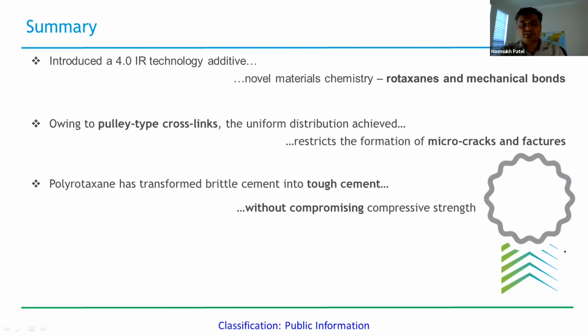I have also demonstrated the effect of polyrotaxane, just 1 weight%. It actually transforms brittle cement into tough cement without compromising the compressive strength. Compressive strength is also very important. We have to have some kind of compressive strength within the cement. Basically, for oil and gas application, the cement compressive strength should be more than 5,000 psi. So we are above 5,000 psi, but at the same time we are able to reduce the Young's modulus, basically introducing elastic behavior.